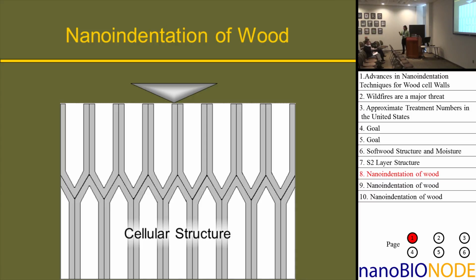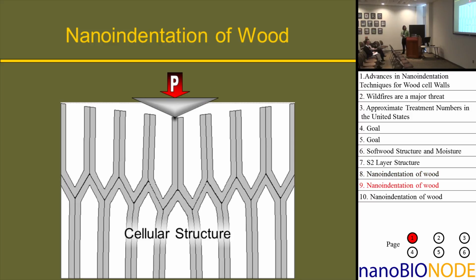Now, of course, these cell walls, especially in late wood, are about 5 microns across. So that's a good size that we can use nanoindentation to test the mechanical properties. But the wood structure isn't exactly the nice homogeneous material that a lot of the standard nanoindentation techniques were developed for. One of the things we realized early on is that if you prepare an unembedded piece of wood, you can have some specimen scale flexing.